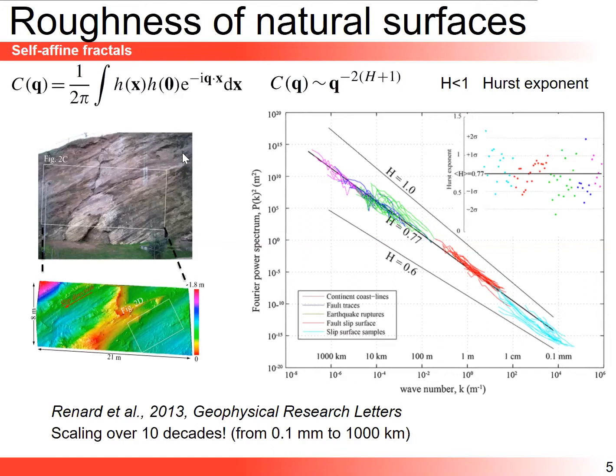And you see in this data of François Renard that you have indeed the power law. This is the straight line. It's a log-log plot, okay? And a power law on a log-log plot is a straight line with a slope here, H, about 0.7. And it's amazing to see that you find a scaling over not 1, 2, 3 orders of magnitude, but over 10 orders of magnitude. Please pay attention to the scale here, from 1,000 kilometers to sub-millimeter length scales. Okay, so roughness is important.